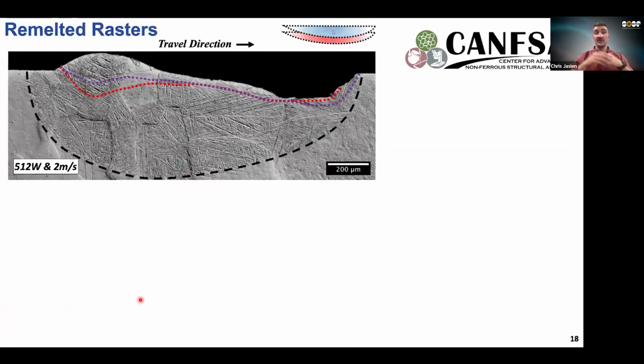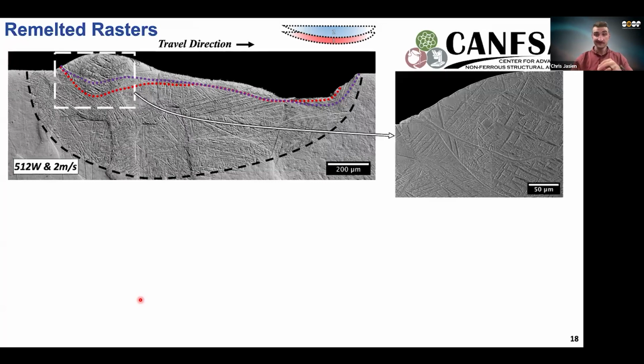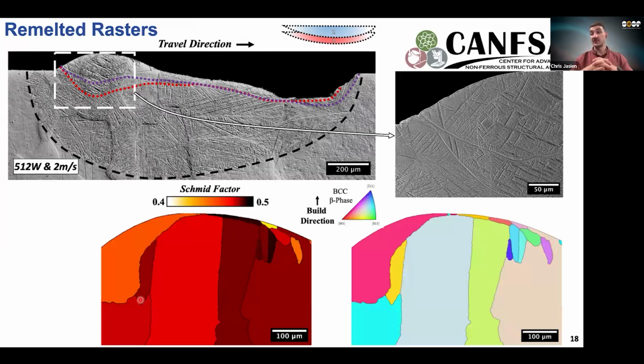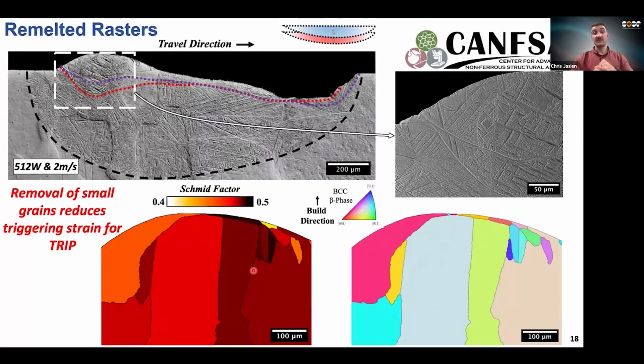And then just to validate that, we went back and performed another experiment with the exact same parameters, but now we remelted the top of it to try to get rid of those small grains at the top, to see if we would get back the response that we would expect. And we do actually get it back. For instance, we see that here we've got large amounts of TRIP in both of these regions, and we see that these are a function of different grains. We see now that we got rid of these very small grains at the top, and we've got a large range of Schmid factors, showing us that as we remove these small grains, we're able to reduce our triggering strain necessary to cause this material to TRIP again.